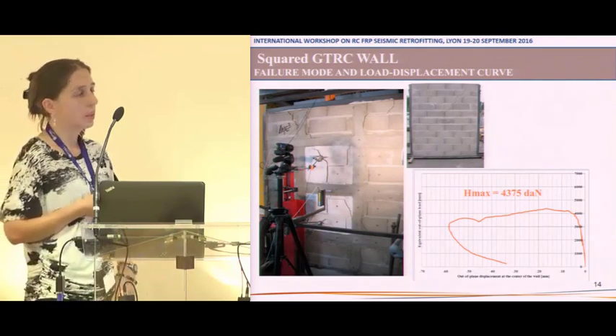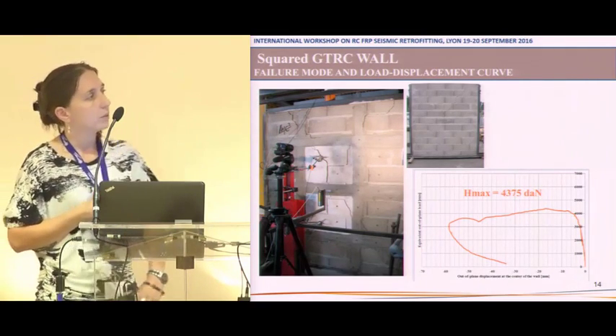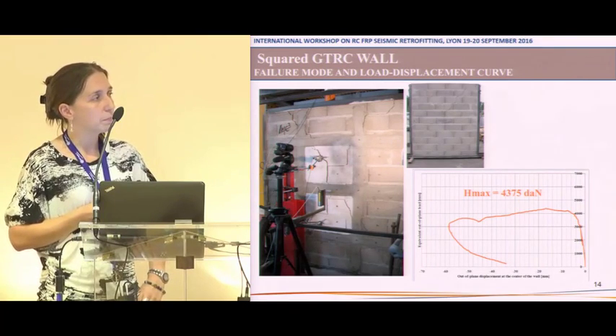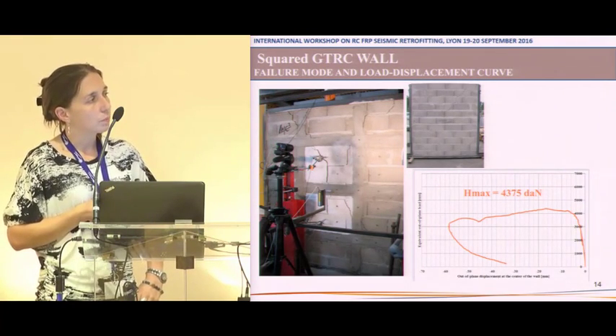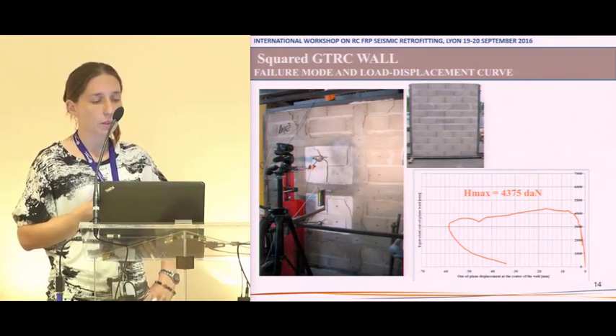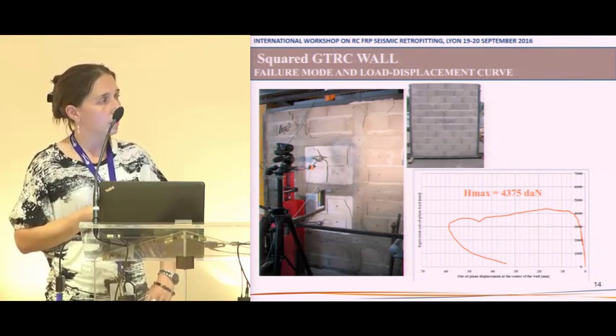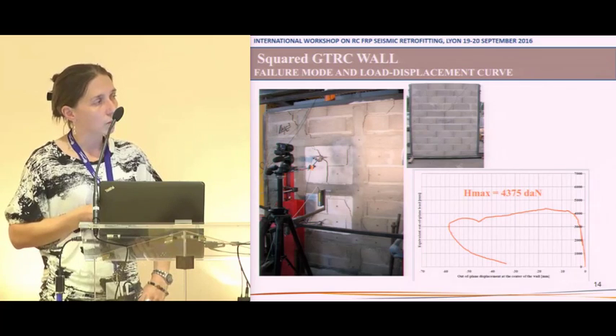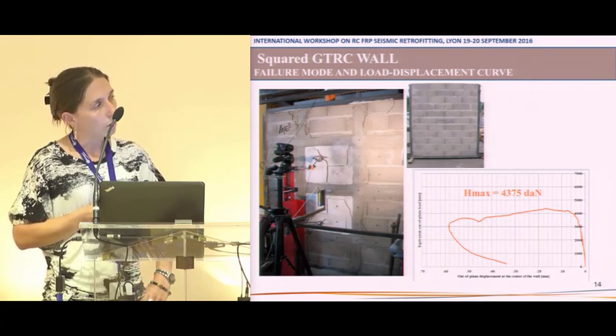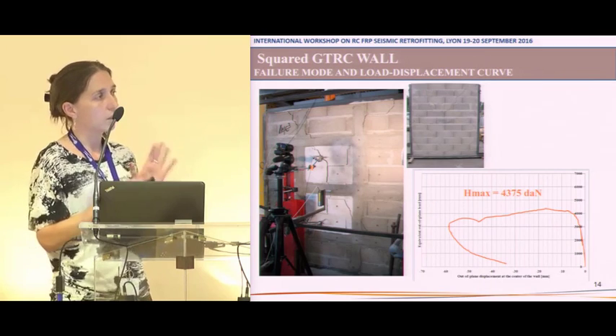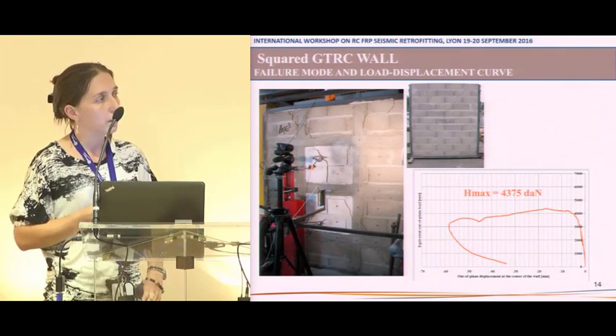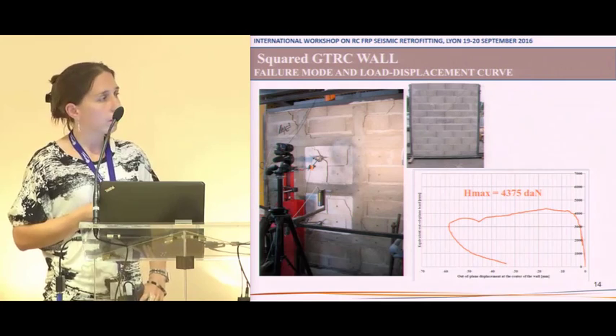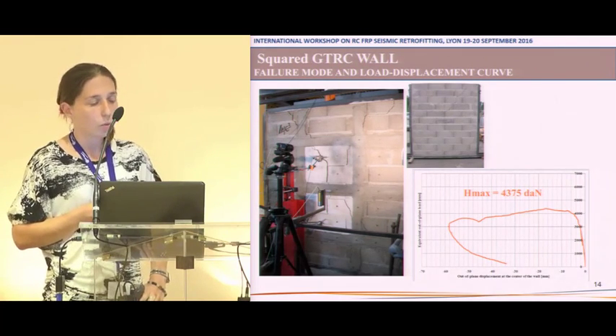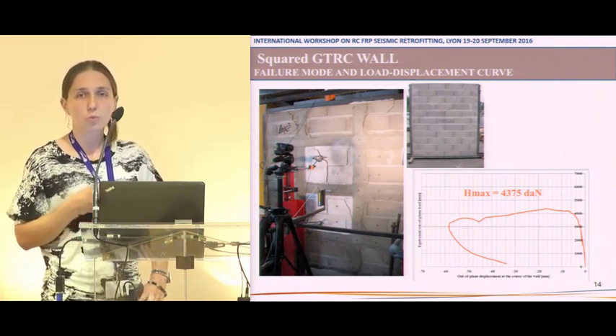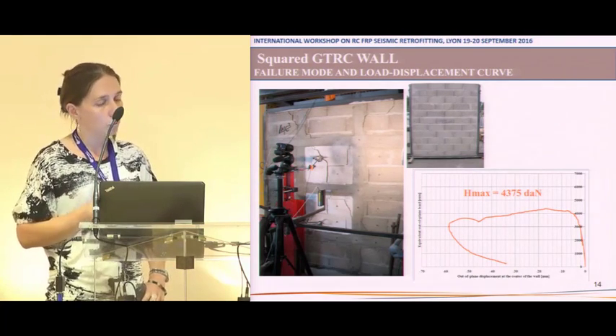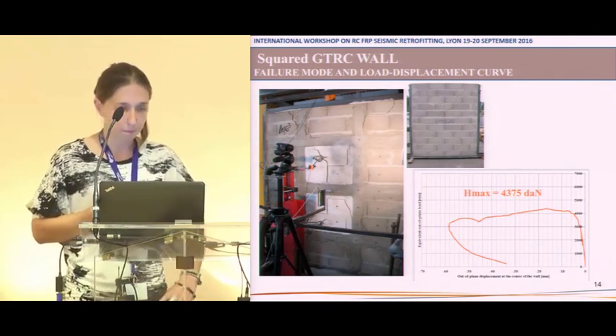Concerning the square GTRC walls, we have the same crack patterns, but we haven't got any failure of the GTRC materials. The first linear phase is not as large as in the case of FRP, but the real difference is in the post-peak zone, where the load loss is really gradual compared to the previous one.